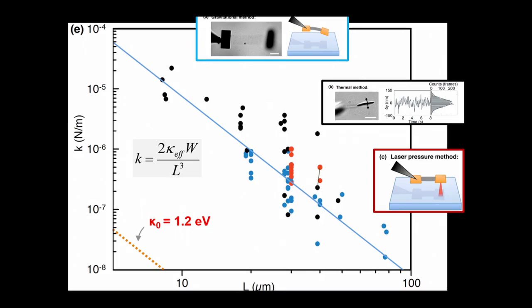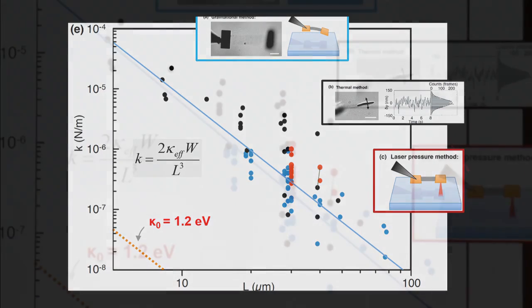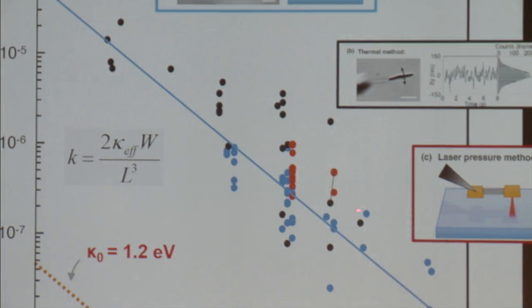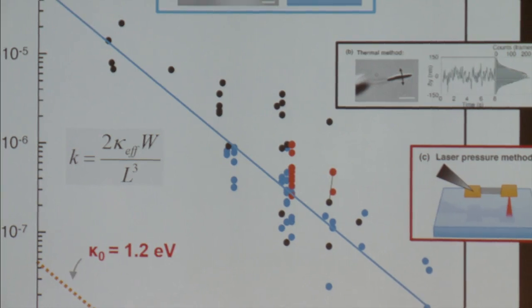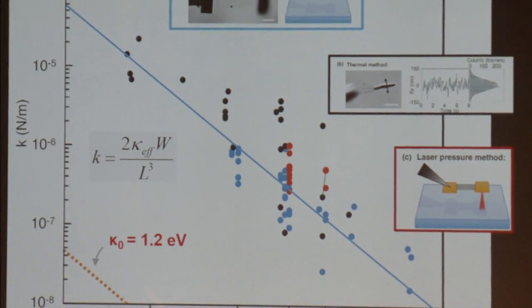Anyway, if we accept we're going to work in water, we can measure, for example, the bending stiffness of these graphene sheets. And this is the spring constant of this graphene sheet. It's a function of how long the graphene sheet is. You don't need to pay a whole lot of attention to this graph other than, number one, we took a whole bunch of data using a whole bunch of techniques. And number two, this is what we got, and this is what we thought we were going to get. And finally, this is a log scale, so we didn't miss by a little. We missed by about 3 orders of magnitude in how stiff the graphene was in comparison to what we thought.